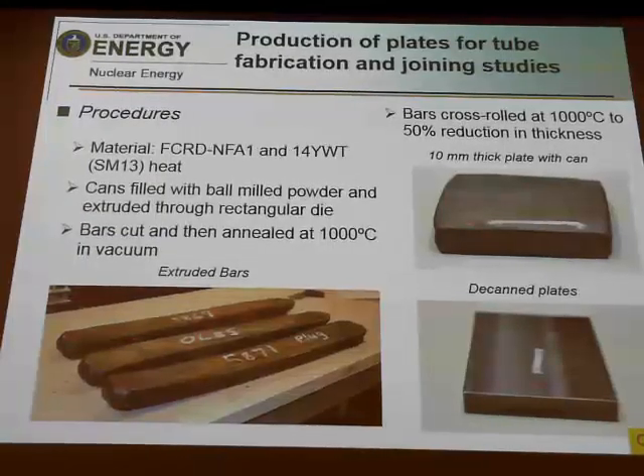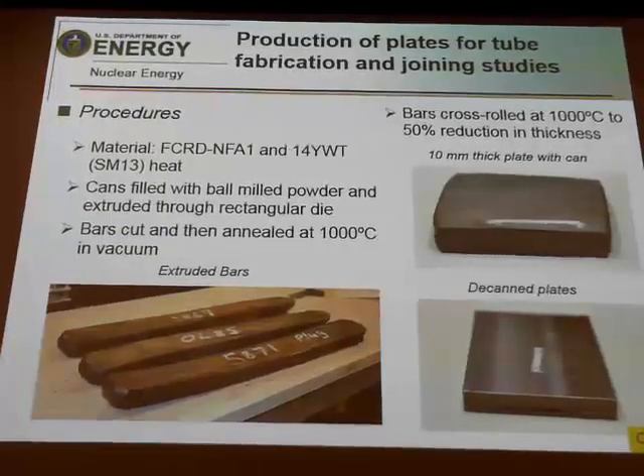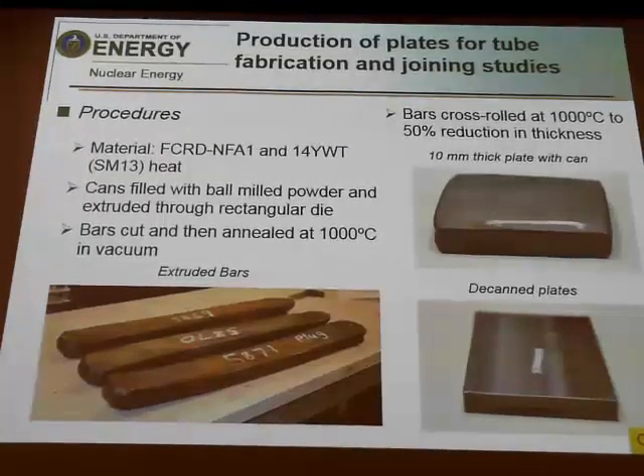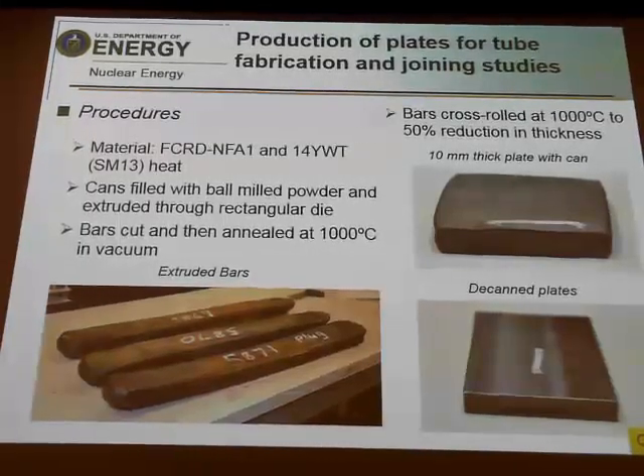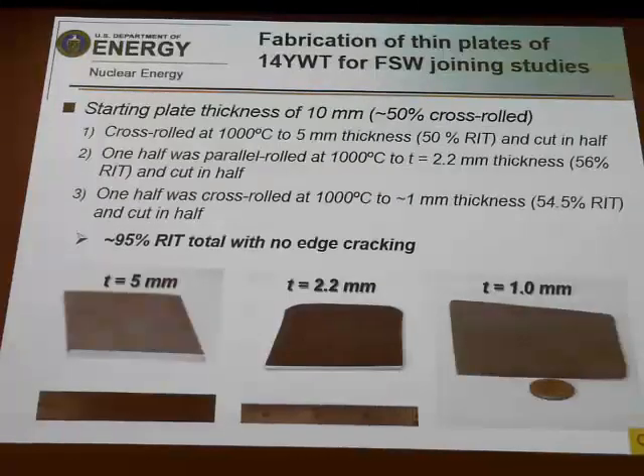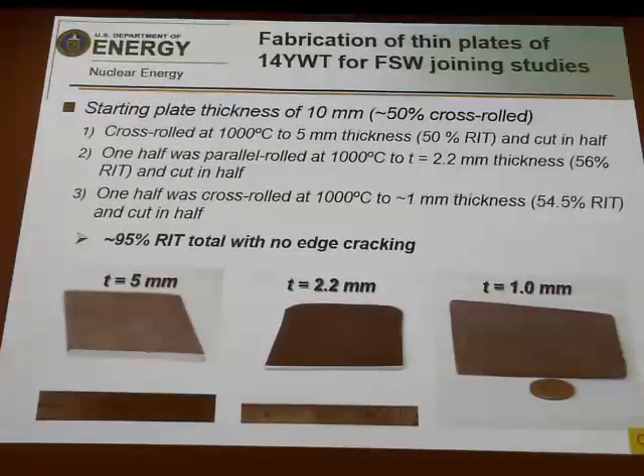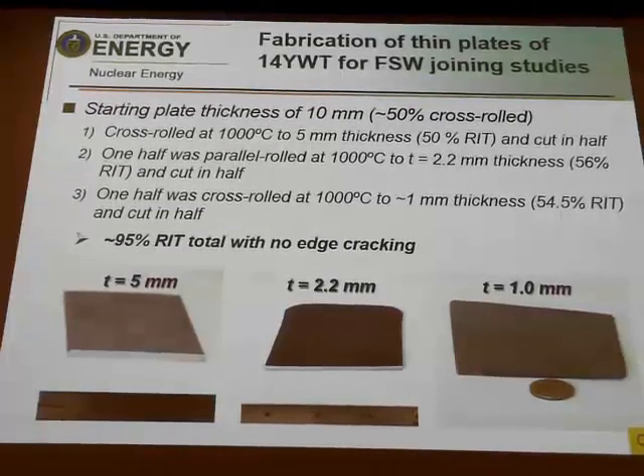We've also extruded them into plate form and then cross-rolled them. In this case, the material was cross-rolled to 50% reduction in thickness, getting it down to about a 10 millimeter thick plate, and then continued to cross-roll at 1,000 degrees C down to 5, to 2, and down to 1 millimeter. This actually went really well. There was a 95% reduction in thickness, and there was no edge cracking in this material. So for a difficult material to process, that went very well.